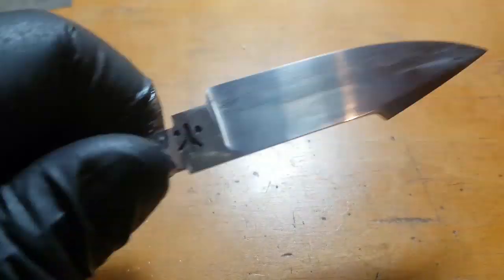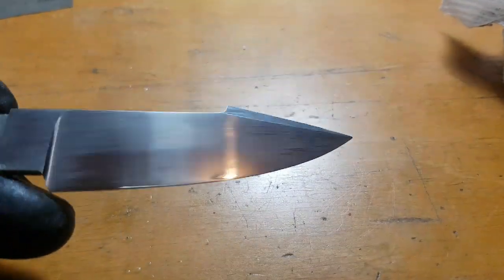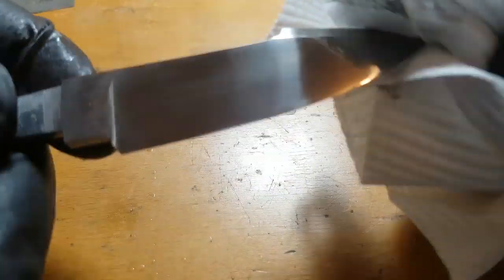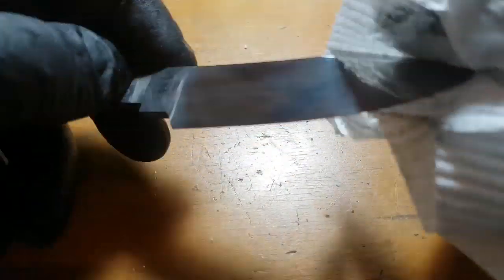In order to achieve that mirror look with the Hamon shining through, I use this metal polish. You can use Mother's Mag or Autosol, but it's got to be a very light abrasive, very light polish, just to remove those surface oxides. And this can be a little bit of a difficult process, takes a little while. And I'll do this every 15-20 minutes of etching, I'll do a polish.